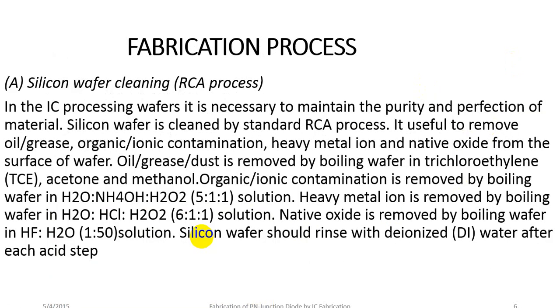The first fabrication process is silicon wafer cleaning using the RCA process. It is necessary to maintain the purity and perfection of the material. The RCA process removes oil, grease, organic ionic contamination, heavy metal ion, and native oxide from the wafer surface. Oil and grease are removed by boiling the wafer in trichloroethylene (TCE), acetone, and methanol.